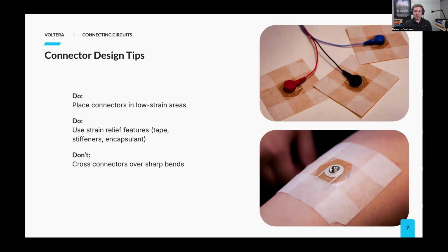In our gold electrocardiogram (ECG) electrode project, we printed gold traces on a TPU and integrated a snap connector. To reduce strain on the connector, we laminated a PET insert beneath the connecting area. This prevented the TPU from overstretching the gold ink, which could become brittle under elongation. As a result, the design maintained reliable signal performance even after repeated flexing.